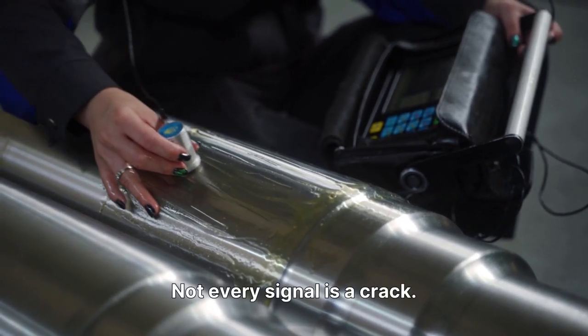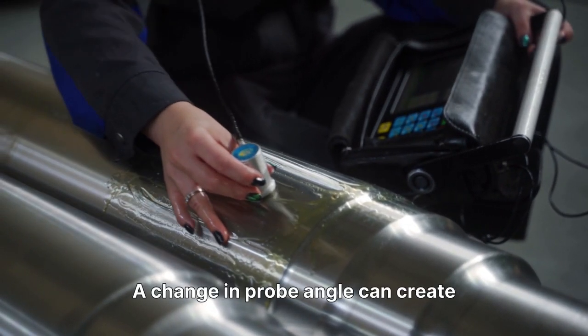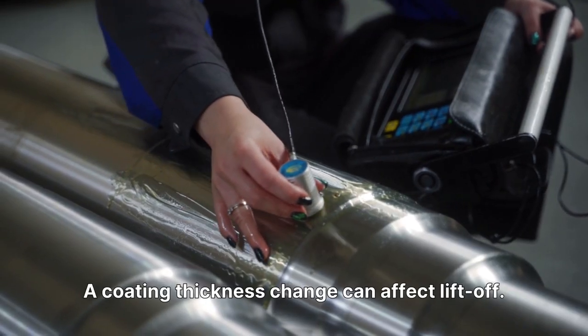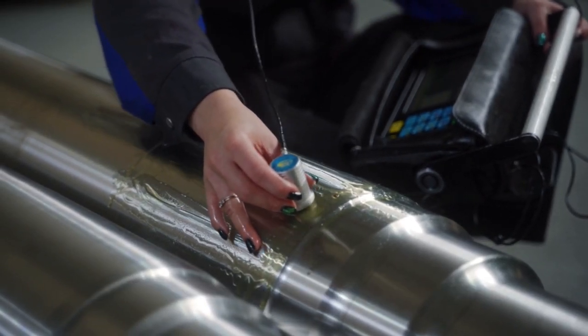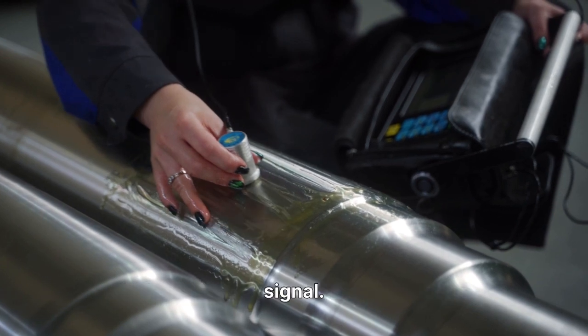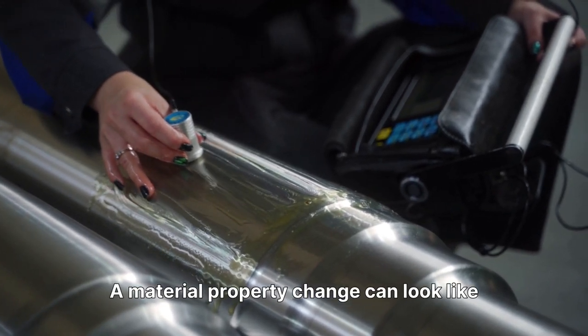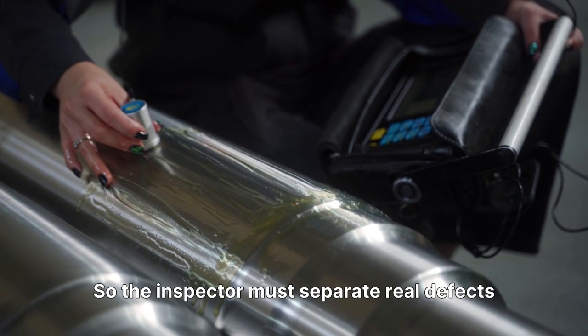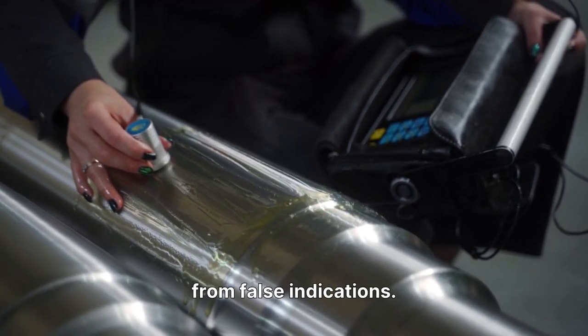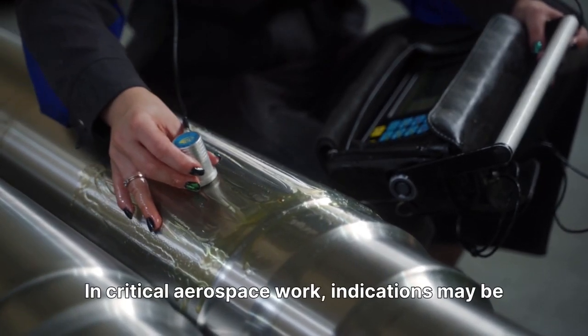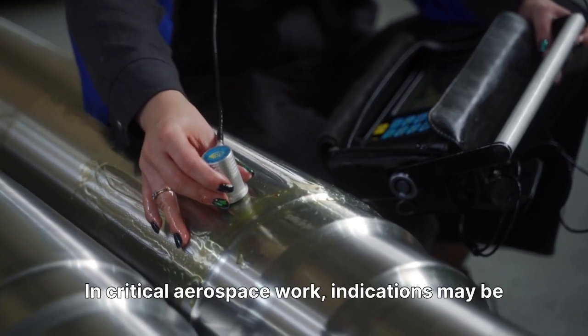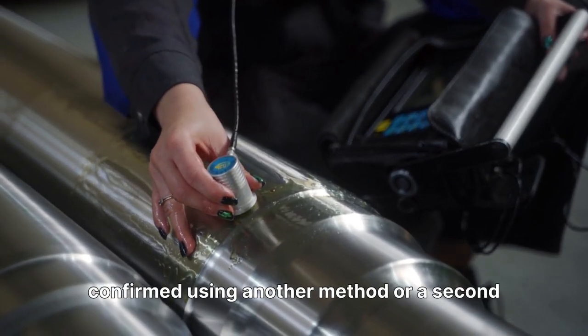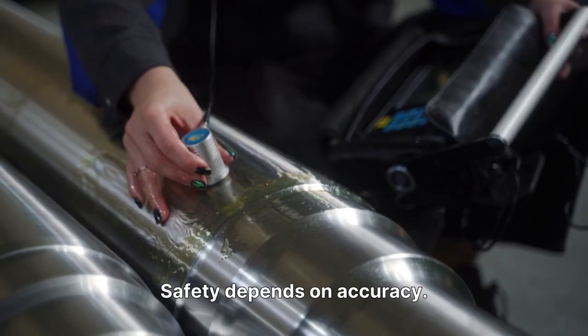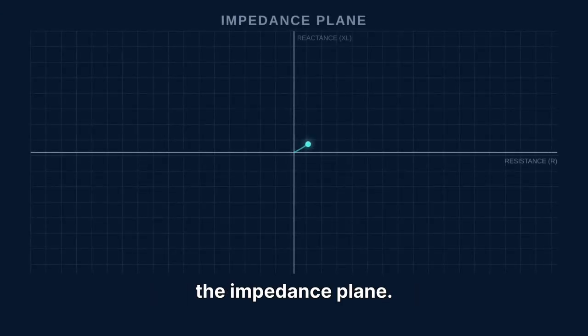Not every signal is a crack. A change in probe angle can create noise. A coating thickness change can affect lift-off. A sharp edge can produce a geometry signal. A material property change can look like a flaw. So the inspector must separate real defects from false indications. In critical aerospace work, indications may be confirmed using another method or a second inspection technique. Safety depends on accuracy.